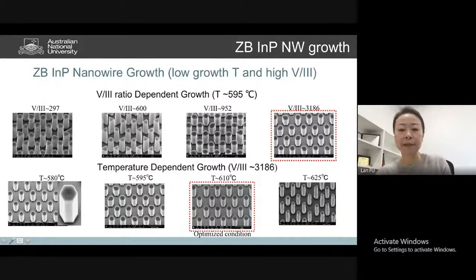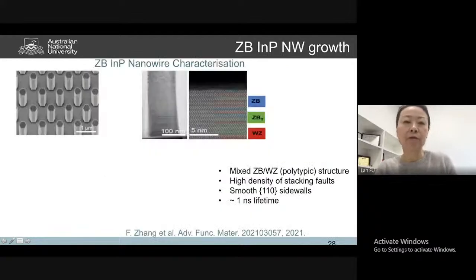You can see the optimization of the shape as well as the morphology of the nanowire. So we can achieve this optimization through growth conditions from previous wurtzite-based nanowire growth. And if we do the analysis, we do have quite a lot of zinc blende segment being incorporated. You can see that the blue color is zinc blende, and then some transition area.